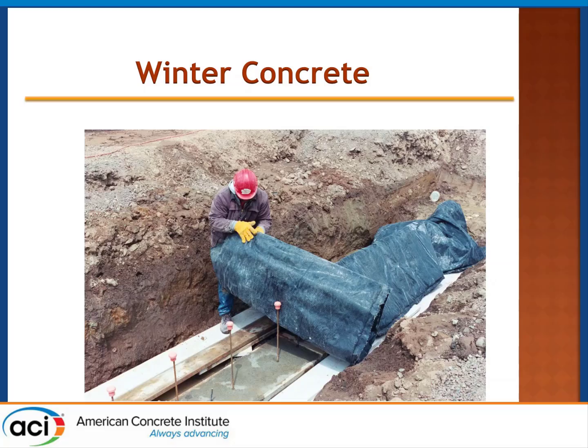And so we ended up heating it up. And of course, that was simply retarded by the presence of the admixtures. Here was one that had worked very well. The contractor was extremely happy with the way it performed. Change one little ingredient, don't do any trial batching or trial placement, and you end up with trouble.